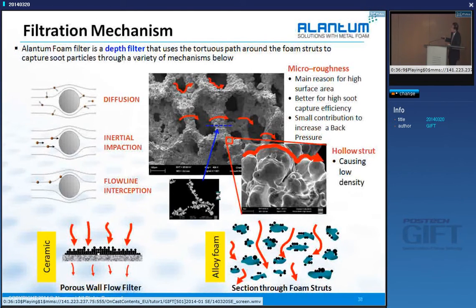Okay, and then I mentioned that the middle of our strut is empty because we just burned off the polyurethane. Then we have a very hollow structure, which means low density. If you compare, ceramic has a very thick wall. It's hard to penetrate this. You can penetrate it, but it creates a high back pressure. In our case, it's open everywhere, so we can reduce the back pressure. Back pressure is very important in automotive applications. Back pressure directly relates to your fuel consumption, fuel economy.